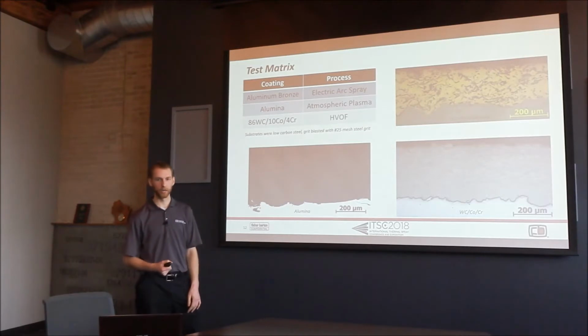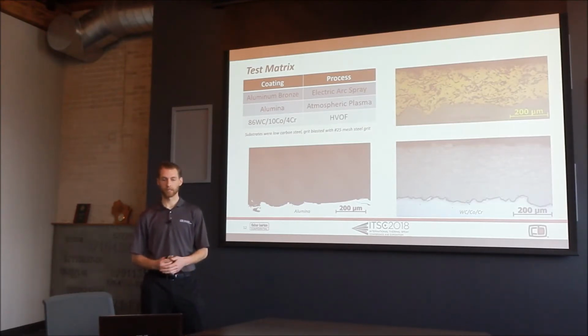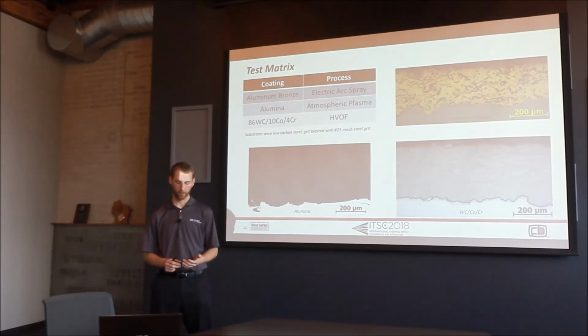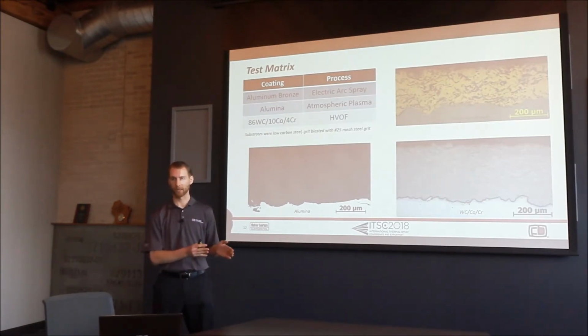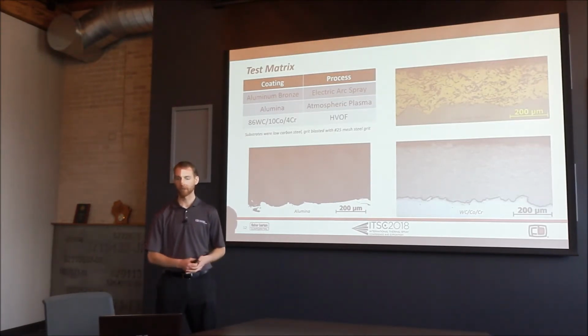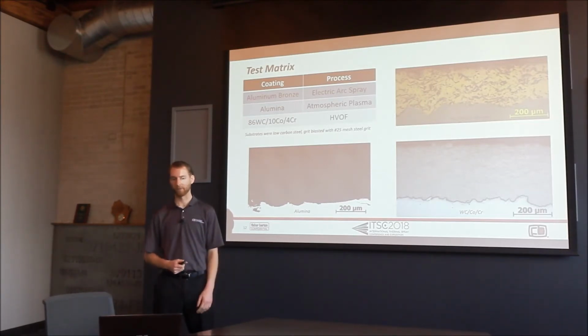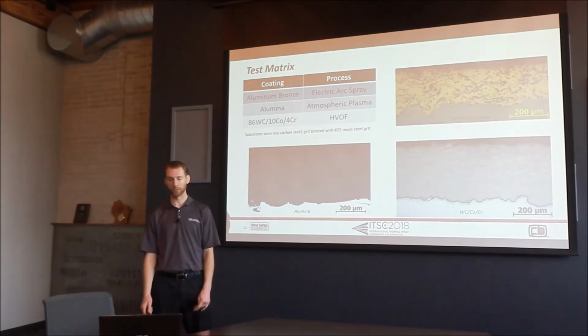So our test matrix here is really a side-by-side comparison. We sprayed the same materials with the same process for ASTM C633 tensile pulls and our 4-point bend. We have aluminum bronze sprayed by electric arc spray, alumina sprayed by atmospheric plasma, and 86WC/10Co/4Cr sprayed by HVOF.